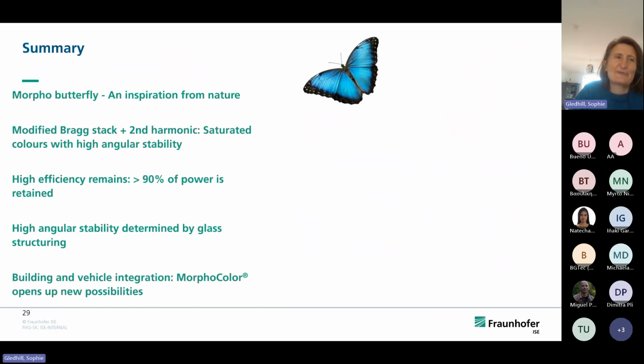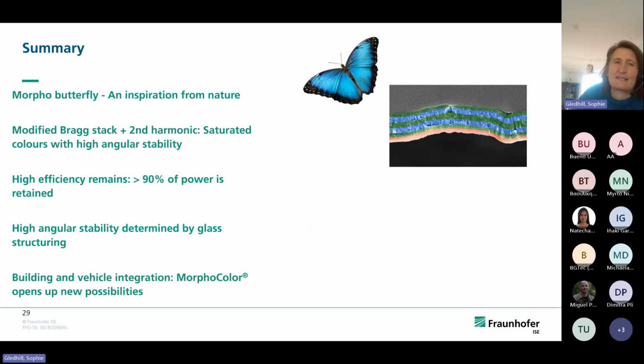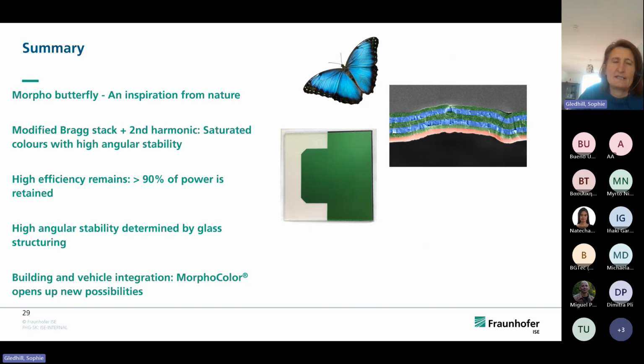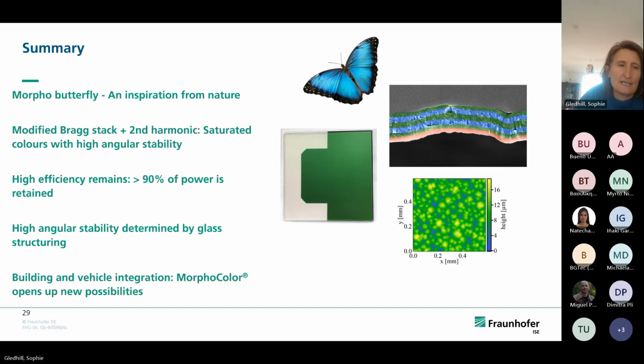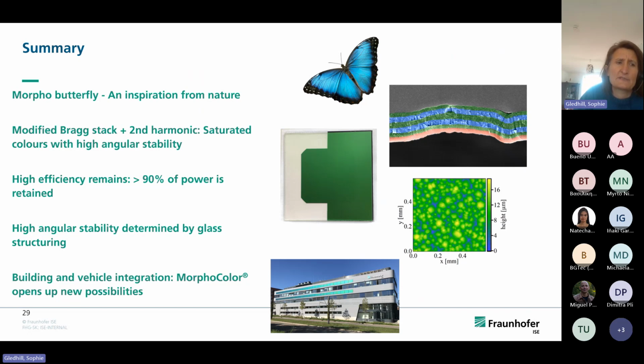So in summary, the inspiration came from the Morpho butterfly. What we have is a modified Bragg stack using the second harmonic, and we achieve our saturated colors with high angular stability. We have high efficiency due to this narrow spectral reflectance, and more than 90% of the power is retained. We have our high angular stability, which is determined by the glass structuring. And this opens up many ways where we can building and vehicle integration of PV using this Morpho color coating.